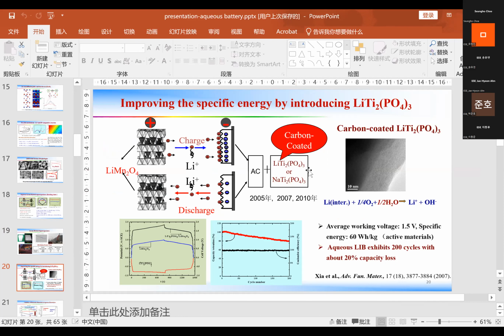introduced lithium titanium phosphate. This material can be synthesized at a high temperature, over 900 degrees centigrade, so normally it has a small surface area. Another point is that it is a strong material with good cycling stability. But the problem is, we use the carbon-coated material, and over 200 cycles, there is still a 20% capacity loss.